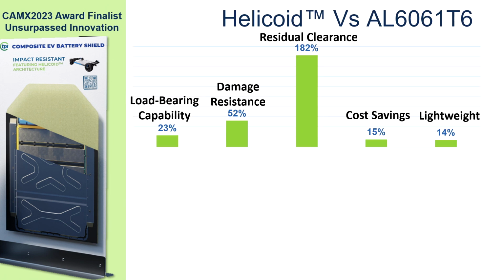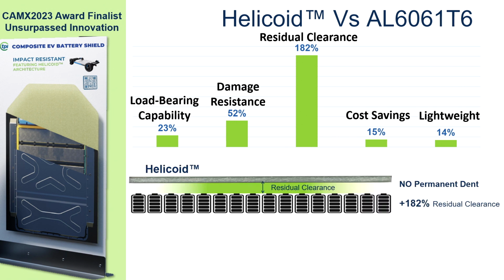The big benefit here is you can see how usually you need to make a compromise between performance, cost, lightweight, but here we are striking through all the key points. You're basically developing a solution that brings you improved load-bearing capability, increased damage resistance, cost savings, lighter weight, and that big advantage, the advantage that you see there in residual clearance is related to what happens after you have encountered the first damage in your structure.